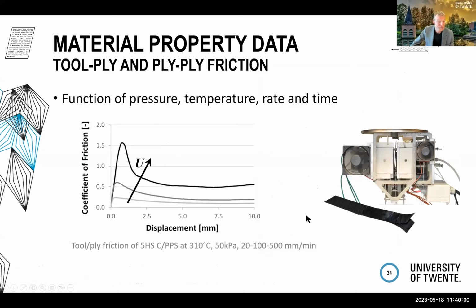This is our setup, which we just mount in a regular tension tester, and a typical response. Let's translate the pulling force to a coefficient of friction and plot it against the displacement of a ply. Then if we do the test very slowly, we reach quickly a sort of steady state friction. Here we have a bit of overshoot, and the faster we go, the more overshoot we observe. So this is something, again, to take into account in the friction model you would use in your forming simulation.